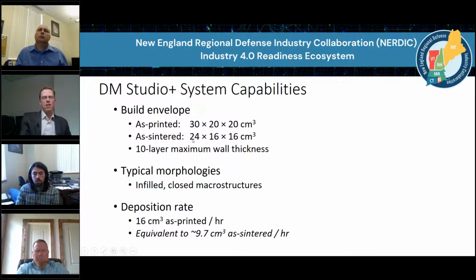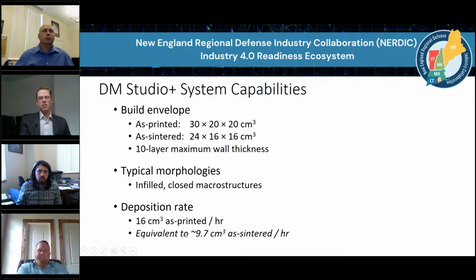So in the as-sintered state, the Desktop Metal Studio Plus system can produce a 24 by 16 by 16 cubic centimeter part. We have a maximum of 10 layers for the wall thickness. For the morphologies, infilled with closed macrostructures are most common. And its deposition rate is somewhere around 10 cubic centimeters per hour for the as-sintered state.